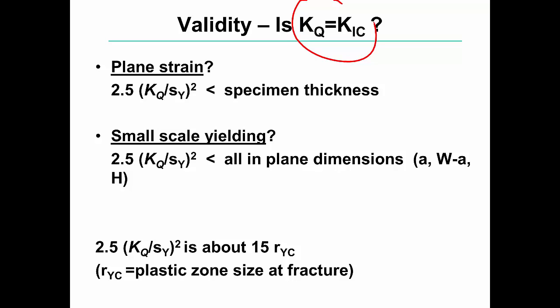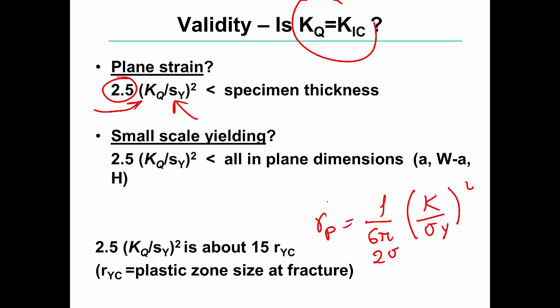Okay, what does that mean? Plane strain means that the specimen thickness must be large. Okay, how large? The recommendation from ASTM is this one here. So you take the value of the fracture toughness in question that you calculated from the test, divide by the yield stress of the material, and you multiply by 2.5. This has units of length. I don't know if you remember, but 1/6 pi or 2 pi, depending on whether you have plane stress or plane strain, times K over sigma y square was the size of the plastic zone.